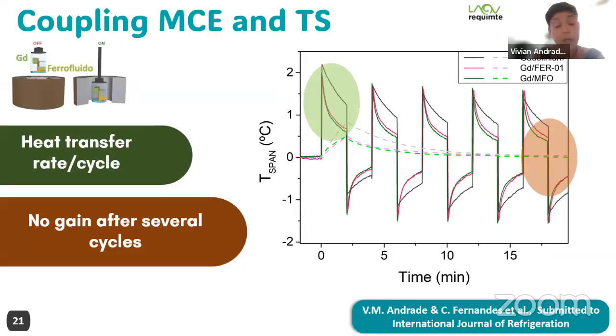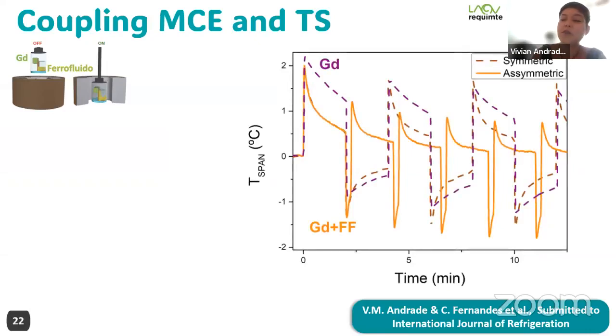But in what was actually a mistake, we got asymmetric cycles, where we gave less time for the material to heat when it's outside the field. So we magnetize and it increases its temperature, and when we demagnetize, it reduces, then increases again before we magnetize again. So we gave less time for the material to heat up before being magnetized again in asymmetric cycles.